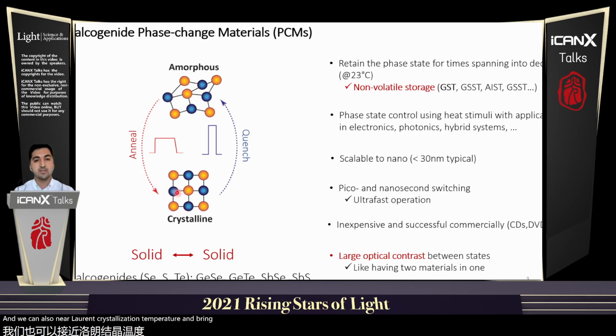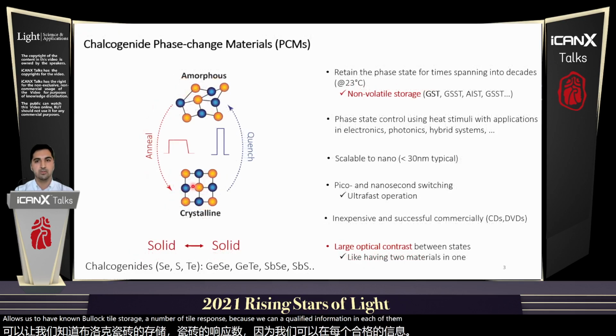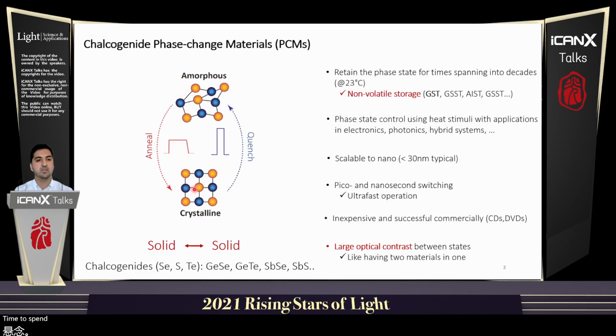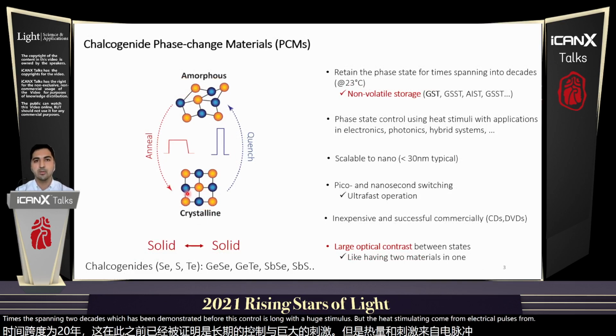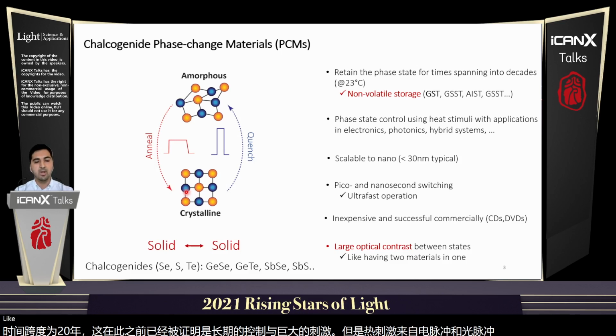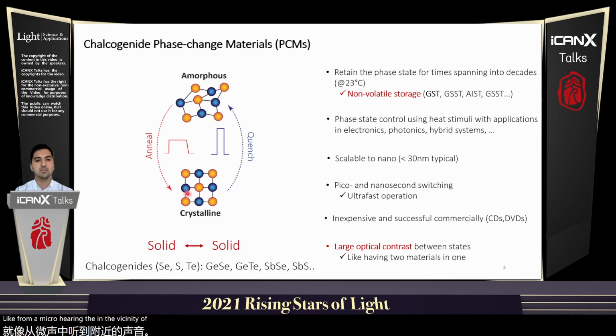Both states are stable, and the fact that they are stable allows us to have non-volatile storage or a non-volatile response, because we can codify information in each of them, and it's going to retain the phase for times spanning into decades, as has been demonstrated before. This control is done with a heat stimulus, but the heat stimulus can come from electrical pulses, from optical pulses, or from a microheater in the vicinity of the material. So there are plenty of opportunities when it comes to devices.